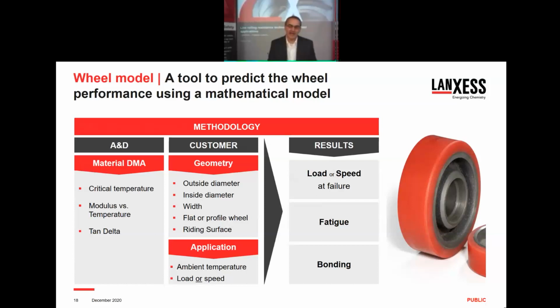Are we riding on a rail? Are we riding, for instance, like a roller coaster, or are we riding on a flat surface, for instance, a forklift in an application in a warehouse? We also look at ambient temperatures, and we look at the loads and speeds. And then what we generally output is the load and speed based on the geometry and the material, and we also look at fatigue and bonding. So the load and speed is usually a hysteretic failure. When is it going to actually internally melt down? When is it going to blow out? We can find that threshold fairly accurately.